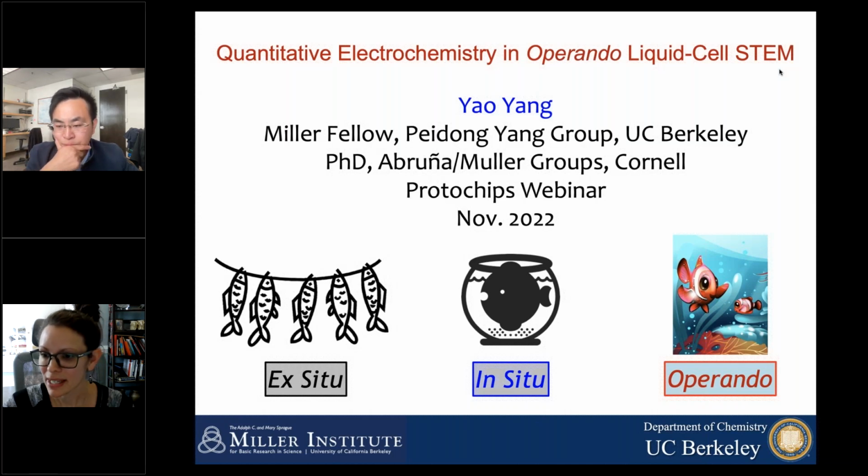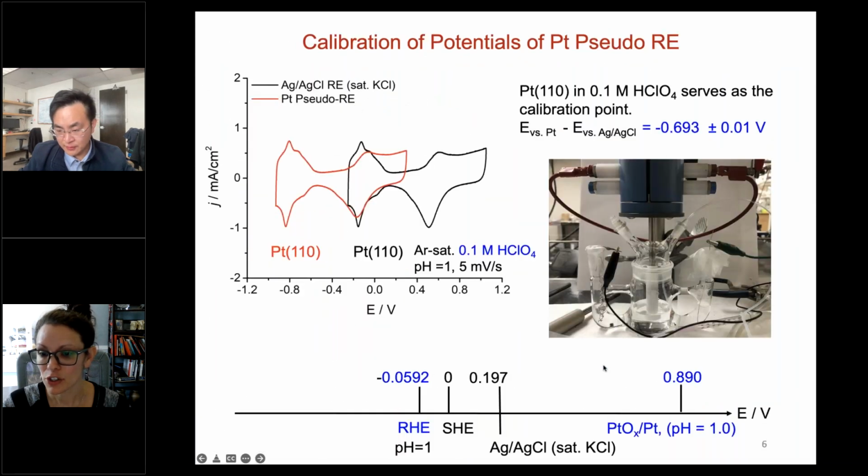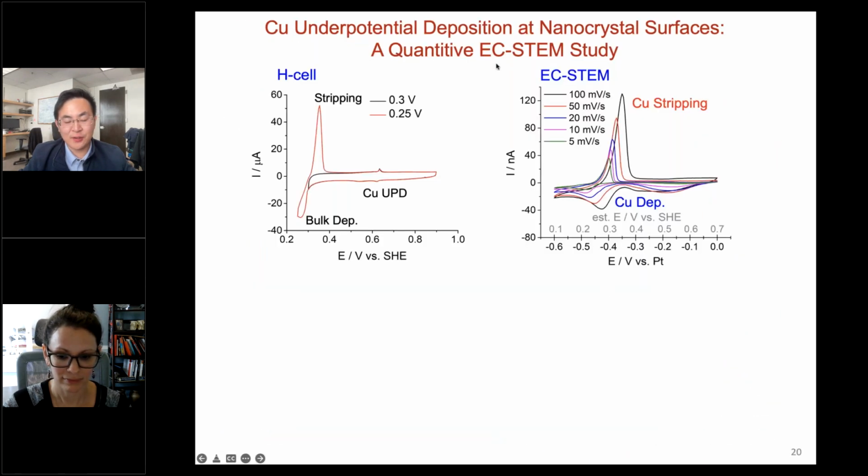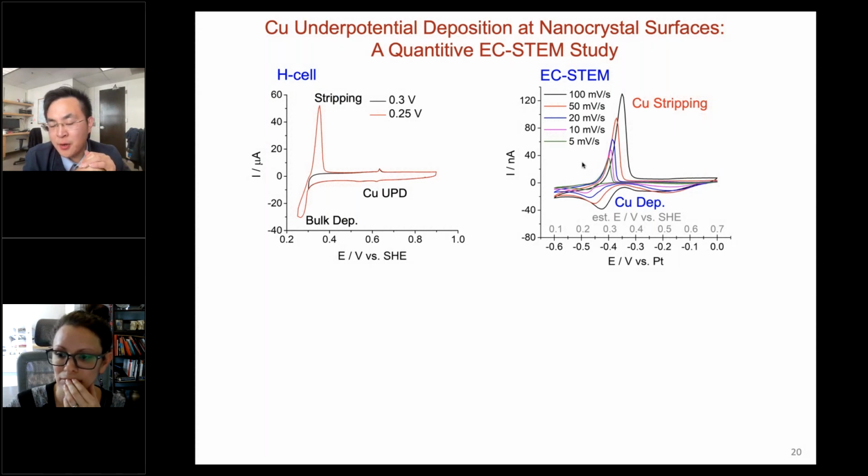Thank you. The next question says, in slide 20, so referring to your slide 20, if you want to go back to that. Sure. Are you comparing the first cycles during deposition or a higher cycle? Oh, very good question. Let me go there. Basically, typically for copper deposition, the first cycle often cleans the surface, which we call a cleaning process. So typically I use the fourth or fifth cycles in this case. The stable CV cycles is what I report by default, unless otherwise specified.